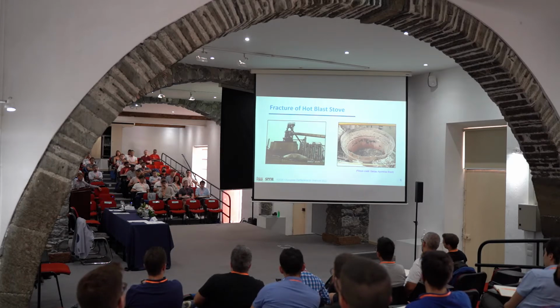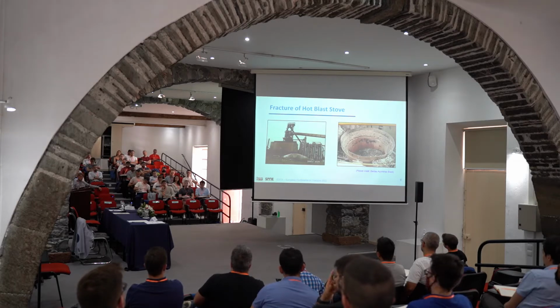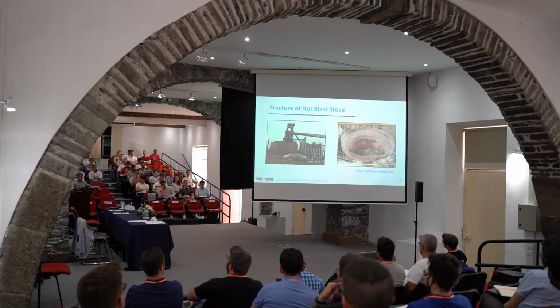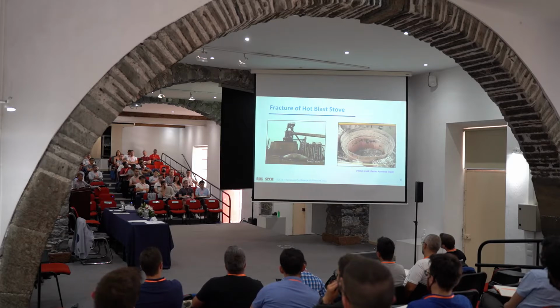And then in 2002, one of these exploded by stress corrosion cracking, because there are a lot of, especially nitrites, some nasty gases that go back to the stoves, and this contaminated the wall of the vessel. And after a certain time, because of the pressure, this literally exploded. So you can see here, this is the dome. It's a piece of more than 200 tons. Okay, and it exploded and passed through the belt. This is the transportation belt for the iron, and landed after almost 150 meters. Okay, so I'm not sure if it's clear, but you can see the size of this piece. You can see the engineers here at the plant looking at the damage.